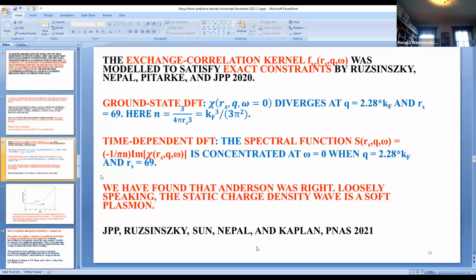We looked at this problem in two ways. First, from ground state density functional theory, we looked at the zero frequency limit of the density response function, and found that it diverged with our model kernel FXC. It diverges at Q equals 2.28 Kf, exactly the critical wave vector, and at RS equals 69, which is in the range of allowed values consistent with the Ceperley and Alder quantum Monte Carlo calculation.